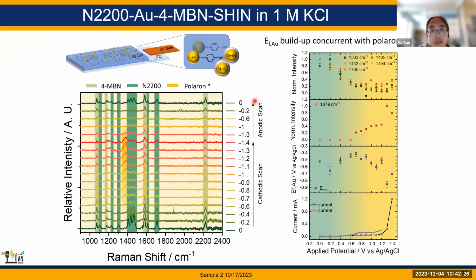And I listed the whole Raman spectra under the cathodic scan and anodic scan here. So basically, during the experiment, we can capture the N2200 features and also the nitrile features together. The dark green features stand for the N2200. We can clearly see that the N2200 starts to reduce in terms of intensity. And meanwhile, there are new features that occur, which are attributed to the polaron formation. And the light green shows the nitrile peak. So this is the CN frequency that we use to extract the Fermi level of gold.